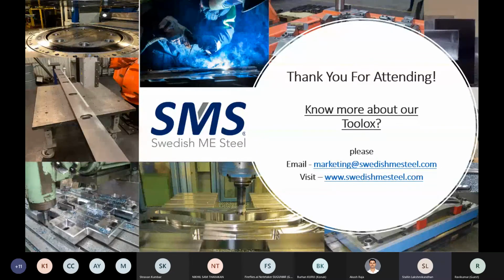Do you have any good steels for this? Because my raw material contains glass fiber. What is the glass fiber percentage, sir? More than 40%, sir. If it is more than 40%, then you can go for Toolox 44 plus nitriding. What life do we get with that, sir? Currently, our tool sustains only around 80,000 shots. What material do you use? Currently, we are using P20 high hard, provided by local vendors.